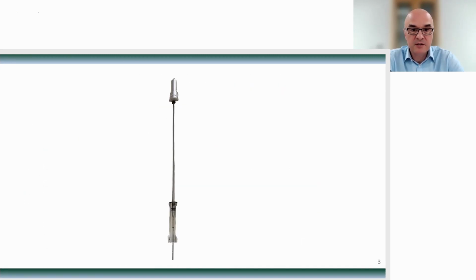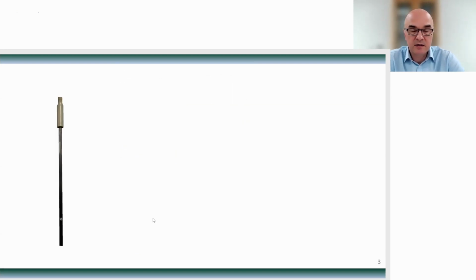The most efficient way to cancel unwanted magnetic signals is to use a long and homogeneous sample holder. Because if you think about it, if you can see my mouse, the sample here will sit right in the middle between two pickup coils. There will be a pickup coil somewhere here above the sample and another one just below the sample. Now, if you make sure that the material of the sample holder is the same above and below, then the coils will not notice the movement of the holder. So the long story short, is that if you use a long sample holder and place the sample away from the end of it, whatever magnetic background the sample holder may have will be cancelled.